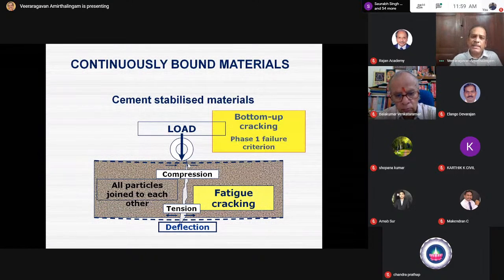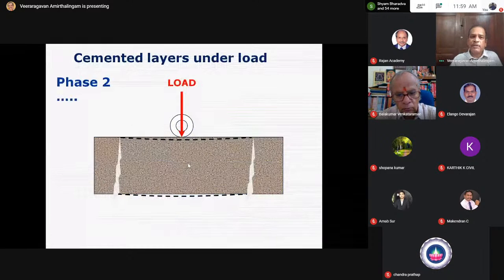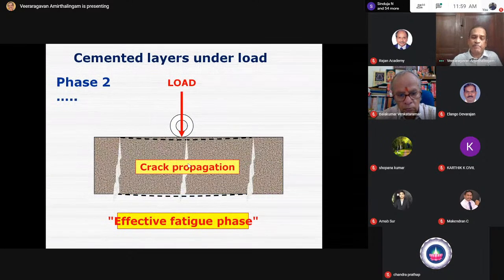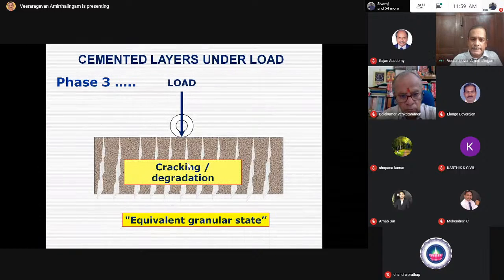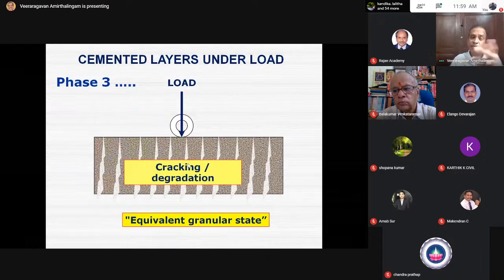It will come to the top of the bituminous layer. But this crack is phase 1. It will become more cracks under repeated loads. That is an effective fatigue phase. So eventually in phase 3, the layer will totally crack, and the modulus of the layer will be equal to a granular layer. Now, I have assumed 5000 MPa as a modulus. It has cracked. It has come to 3000 MPa. It has cracked. It has come to 2000 MPa. It has cracked. It has come to 1000 MPa. Now, I designed a pavement assuming 5000 MPa. Is it right? No. Then what modulus should I consider? Should I consider 1000? Maybe it was worthwhile.